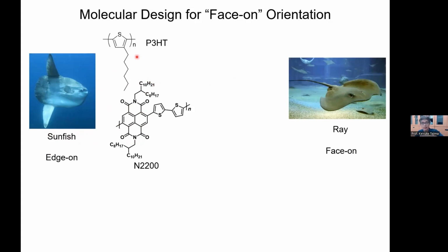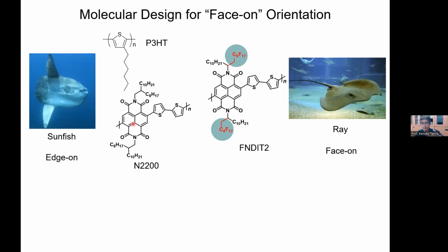As I said, the alkyl chain tends to have a lower surface energy, so it's natural to assume the edge-on. How to achieve this orientation? The answer we came up with is that we have this branched alkyl chain, right? So what if we replace one of the branched alkyl chains with this fluoroalkyl chain?